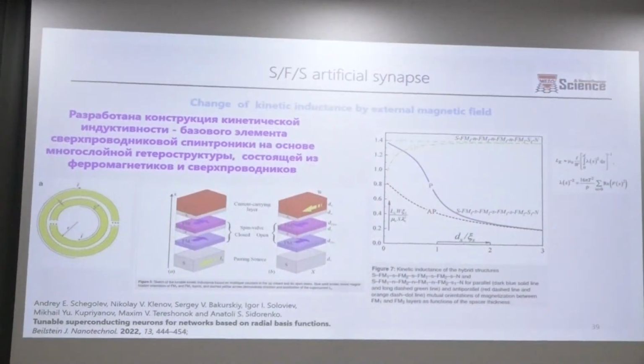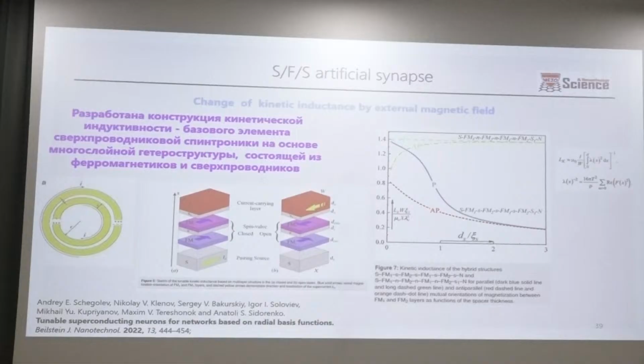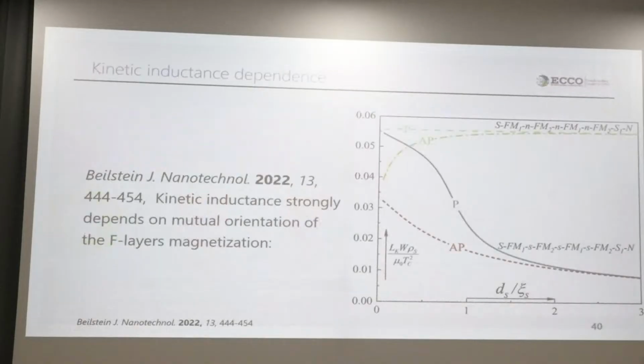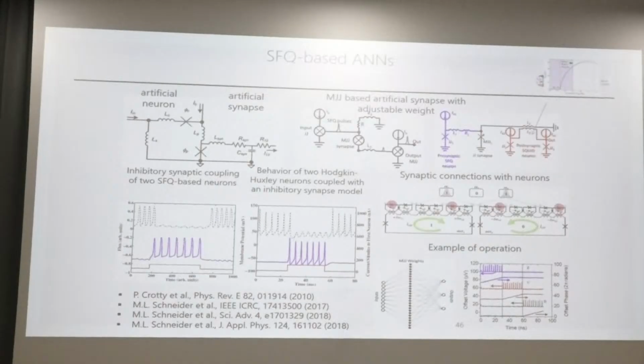On the right panel, you can see the red dotted curve. This is for anti-parallel magnetization of such a metamaterial. The blue curve is for parallel magnetization. That's why, changing the magnetization of such a structure, we can change the impedance of such an element. And here one can see the circuit consisting of an artificial neuron based on those Josephson junctions and an artificial synapse based on this metamaterial, and the spikes which go through this circuit, which can be used in a perceptron. On the bottom you can see the perceptron. This is one part of a neural network which can be used for recognition of images.